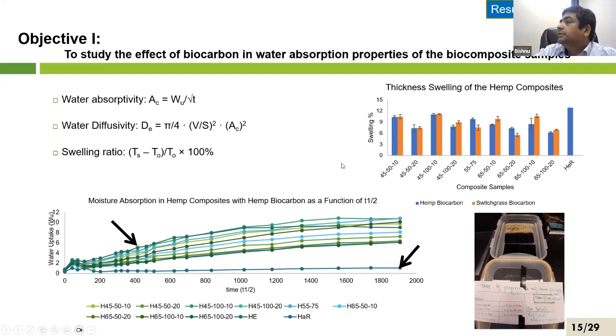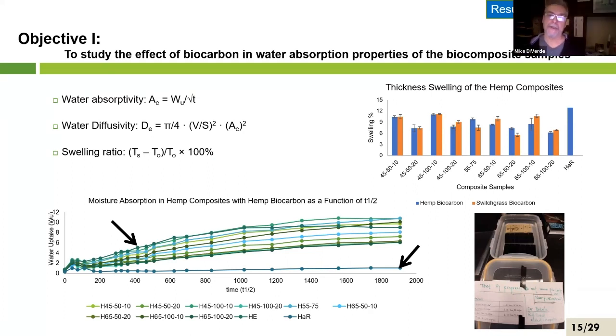Okay. And then we also did the swelling test. And then we also found that the swelling was lower with the addition of the biochar. Which again says that the moisture absorption is lower. On your designations there, the first number, 45 as versus 55, 65, is that indicating the percentage of biochar?